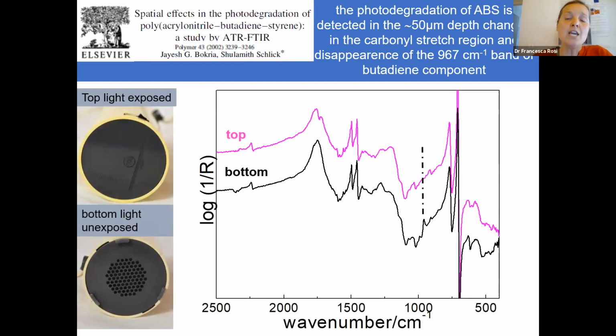And effectively, if we look now in the mid-infrared range to the spectra recorded on the black cap, on the top light exposed and the bottom light unexposed, we clearly see that butadiene has disappeared in the light exposed, while it is still present in the bottom.